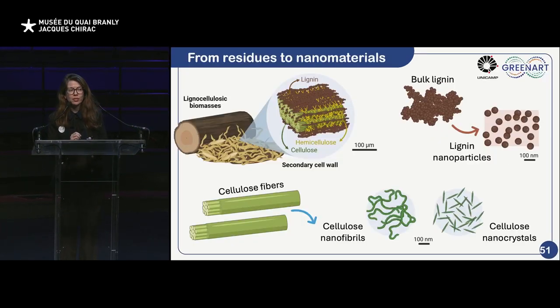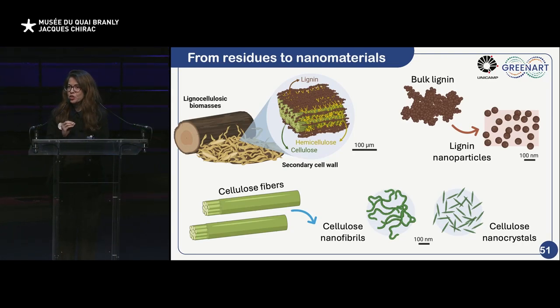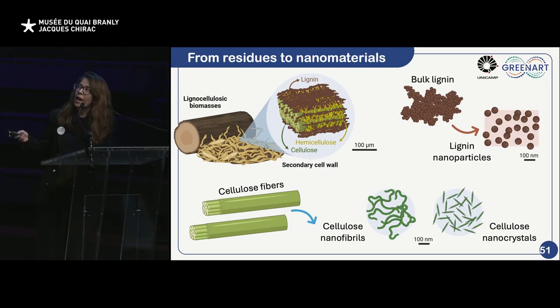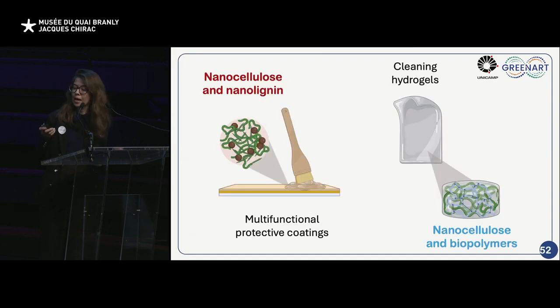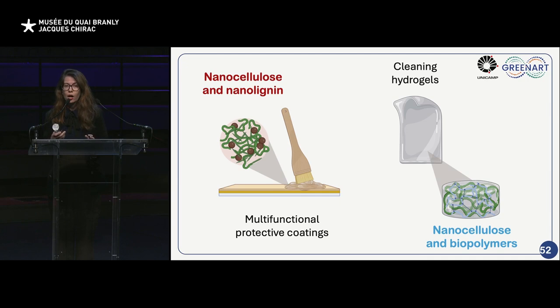So we use agroindustrial residues as the feedstock to produce nanoparticles, nanomaterials. We can extract cellulose fibers from these residues, and then we convert it into cellulose nanofibrils and cellulose nanocrystals. And also we extract bulk lignin in macro scale, and then we convert it into lignin nanoparticles. And our group in Brazil, in the framework of GREENART project, we focus on two main tasks: the development and evaluation of multifunctional protective coatings and the cleaning hydrogels.